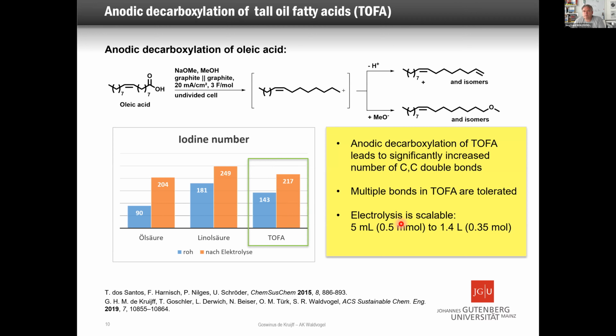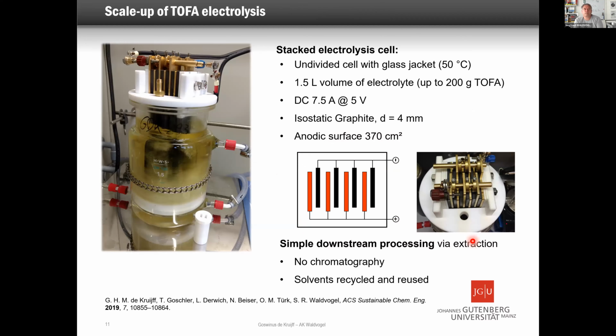And the electrolysis is scalable. We started at 5 milliliters and we went up to 1.4 liters. And then you see, okay, with this amount, you can do something, you can play around. And I think this is the important thing. How does a typical cell look like? What we have here is called a stacked cell. That means you have to contact all of the electrodes. These are graphite electrodes. And you just have to cool it on the outside to keep the temperature constant.